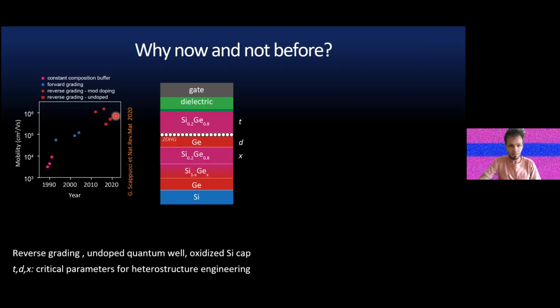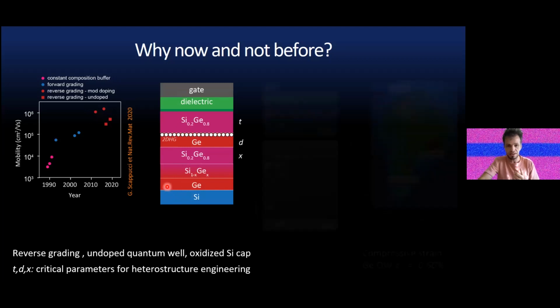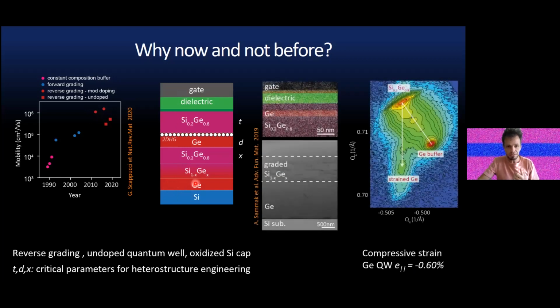So the key enabler was to really swap and do reverse grading. And here you see an image of what this means. It means you actually put a layer of germanium directly on silicon, and under certain conditions, the top part of the layer is very nice and clean, and people actually do photodetectors with germanium on silicon. And then you grade in a small amount of silicon, so the gradient you have to fulfill is only 20%, meaning this heterostructure can be much thinner and with fewer defects. And the topmost part here of the virtual substrate is really nice and clean.